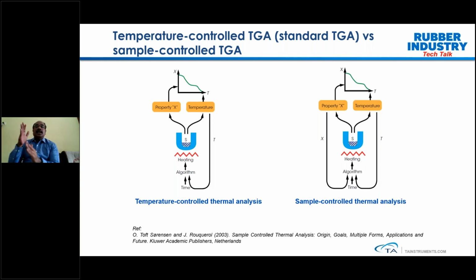So what happens is, at the beginning of the run, the sample will be heated at a faster heating rate. As soon as the TGA senses there is a sample weight change, it will slow down the heating rate and allow that particular decomposition to complete. This way it will have a dynamic heating rate. So depending on the pattern of how the sample is going to decompose, the control mechanism and the associated heating rate are also going to change, and that we call dynamic heating rate, high resolution TG.